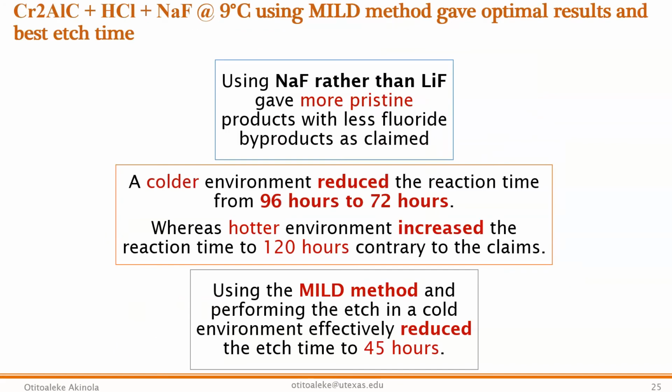After doing this, I got to a sweet spot, and I realized that using HCl plus sodium fluoride at 9 degrees centigrade using the mild method gives me the best reaction product. I was able to reduce my reaction time from 96 hours to 45 hours on average. Also, I realized that the number of impurities in my products was significantly reduced as well.